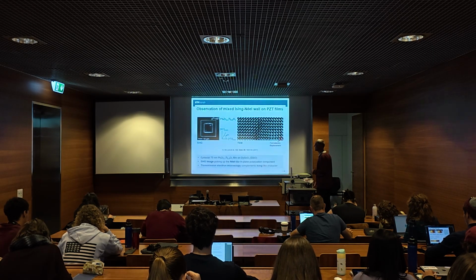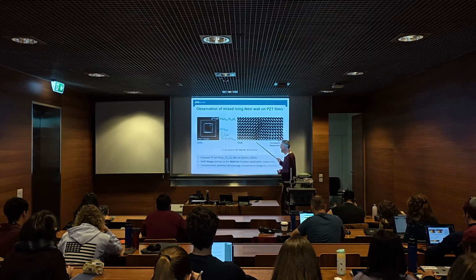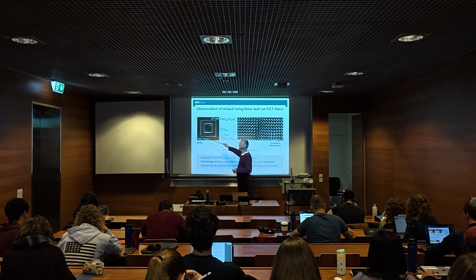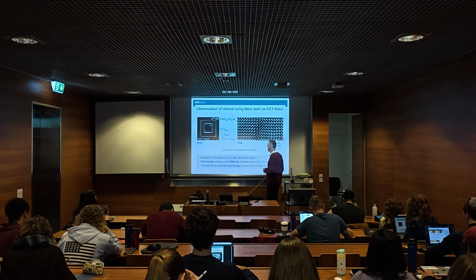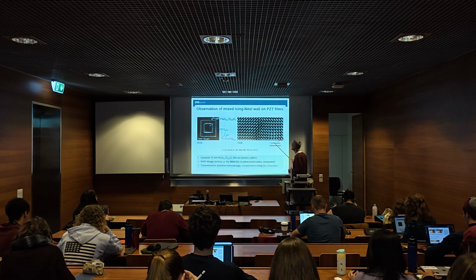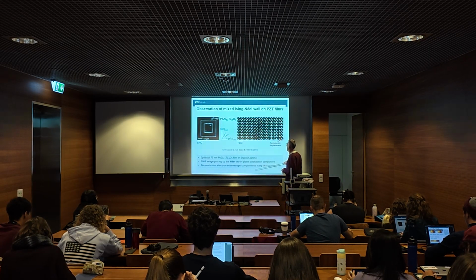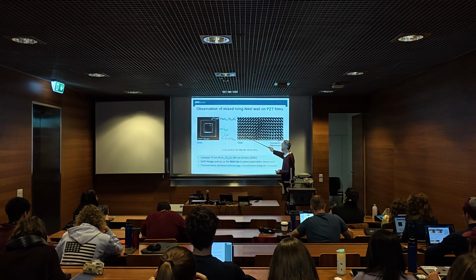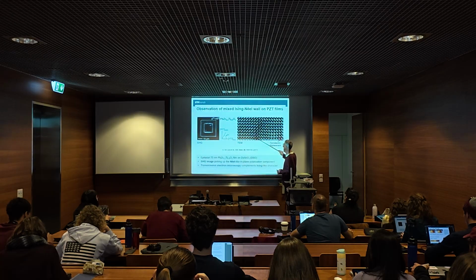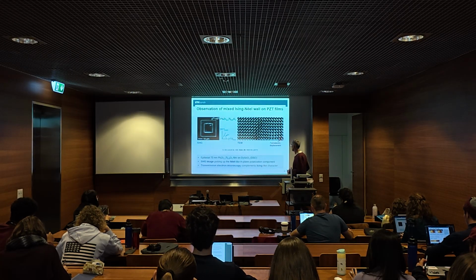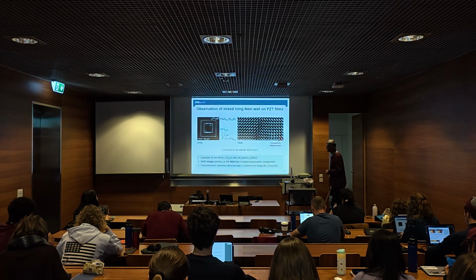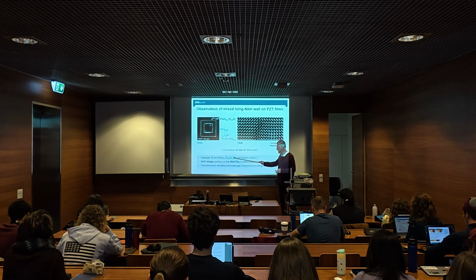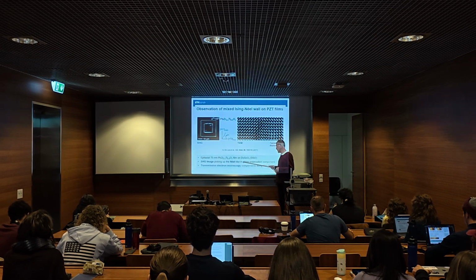Here's the experiment that shows that you can actually have this mixed Ising-Néel wall character. You can image these domain walls with this frequency doubling technique that I just introduced, and you can also do transmission electron microscopy, and then you can see how the atoms are displaced and they rotate. This displacement rotates and shrinks at the same time. So this is mixed Ising-Néel character, here in lead zirconate titanate on a specific substrate.